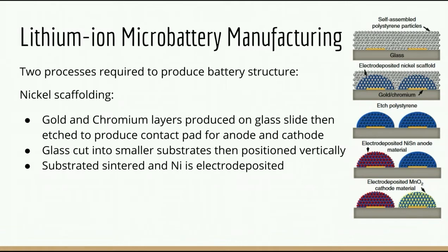Much like the silver oxide batteries, there are 2 different processes required to produce the battery structure: nickel scaffolding fabrication and electrode deposition. The first process is creating the nickel scaffolding. Interdigitated gold templates were produced by sputtering an 8 nanometer chromium layer topped with 70 nanometers of gold onto a glass slide. The gold and chromium layers were etched to produce the contact pads for the interdigitated anode and cathode cells. The glass slide with the gold template is cut into smaller substrates and prepared for polystyrene opal growth.